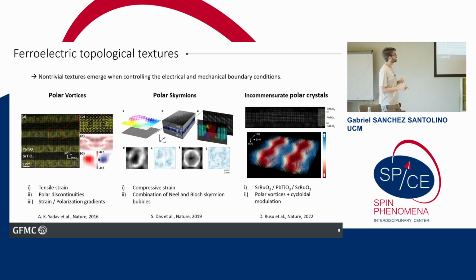And also more recently, people have been trying to make these polar vortices with a chiral modulation in 2 dimensions, in the in-plane and out-of-plane dimensions. To stabilize all these kinds of phases, they had to very carefully choose the material, so you have a polar discontinuity at the interface.